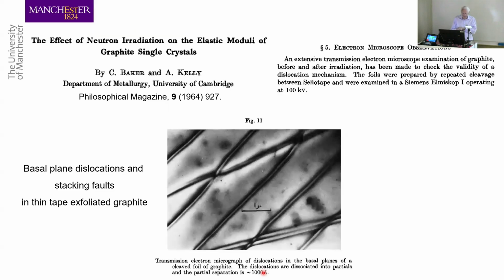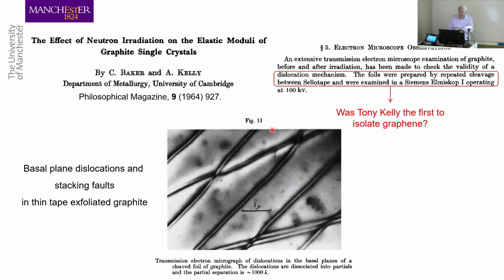But you can go to 1964. This is a paper by Tony Kelly, who Professor Mai knew well, who went into composites eventually. But in his early days, he was working on graphite, doing electron microscopy of graphite single crystals. And he was, would you believe it, preparing his specimens by repeated cleavage between sellotape, between adhesive tape. So he was doing tape exfoliation of graphite. And he was interested in these multi-layer materials where he could see basal dislocations and stacking faults in the material. So we've sort of gone full circle back to the original days.